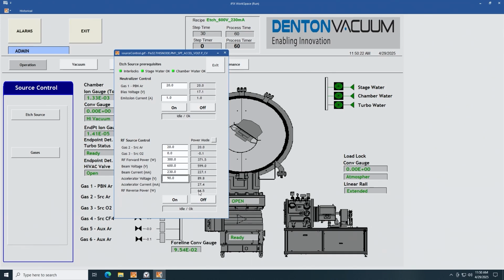And so the solution for that is you can either just run oxygen through the source for about 10 minutes and you'll see this drop to about half of what it is now. But over time you will have to, after like 200 to 300 hours, remove that bowl, clean it, and put it back in. That's a pretty quick maintenance job because you do have to vent the main chamber, but the bowl comes out very easily with a total of 8 screws, and then you can put it back in.